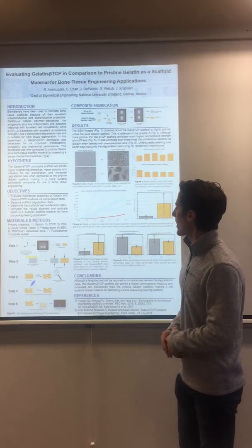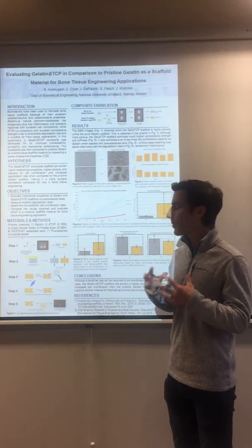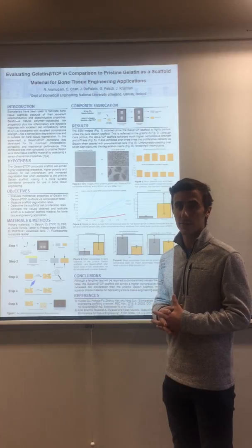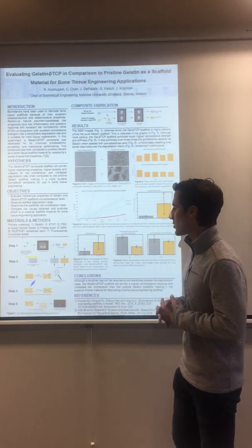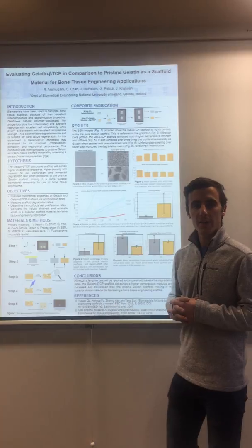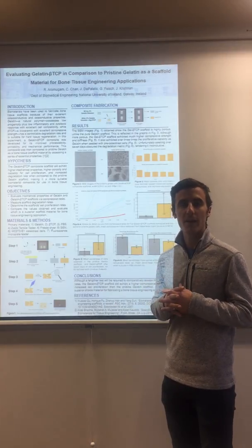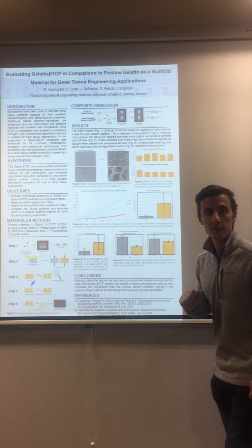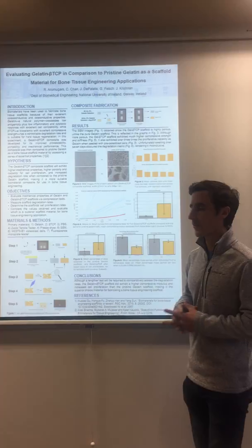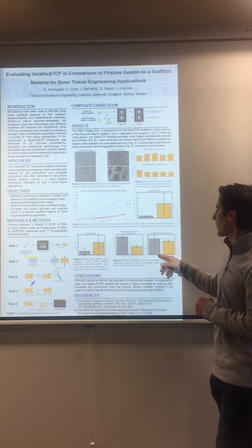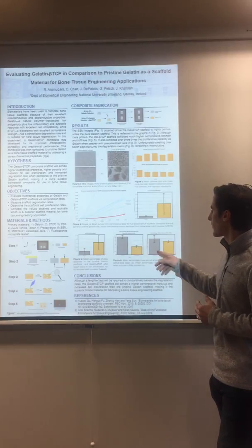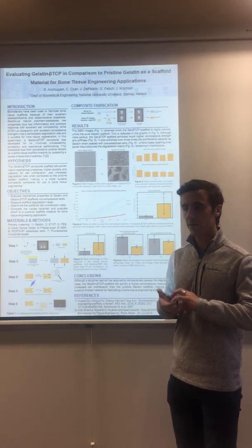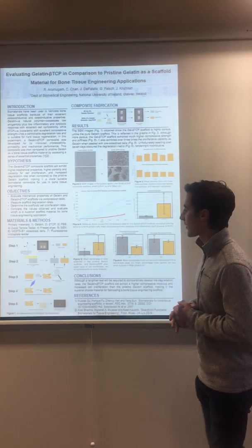that for the gelatin. After doing that test, we massed the scaffolds and then allowed them to degrade for a period of 7 days in solution. We hoped to observe a degradation rate, but because swelling is the dominating factor for the first few days or weeks, it was difficult to determine what the degradation rate is. So in this graph you can see a 3 to 4% swelling rate rather than degradation. So in order to properly get a degradation rate, we need a longer test.